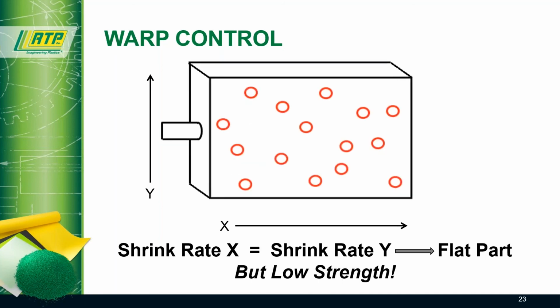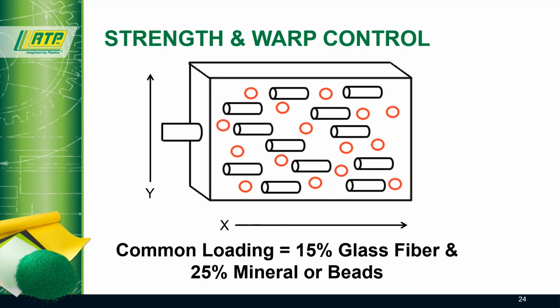Instead of adding glass fiber, one could add a low aspect filler, such as mineral or glass bead. This will reduce shrink rates in both directions and result in a flat and dimensionally stable part. However, low aspect ratio fillers do little to improve strength and stiffness. So what is commonly done in the compounding world is to add a combination of glass fiber and mineral or glass beads. For instance, they might use 15% fiber and 25% mineral. This helps to achieve a dimensionally stable part with strength and stiffness from the glass fiber.